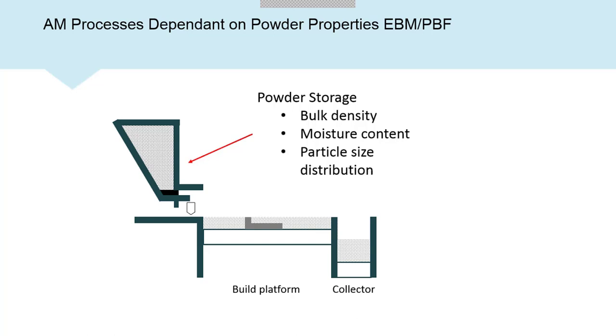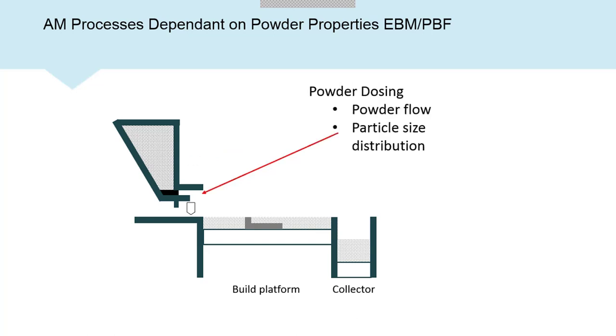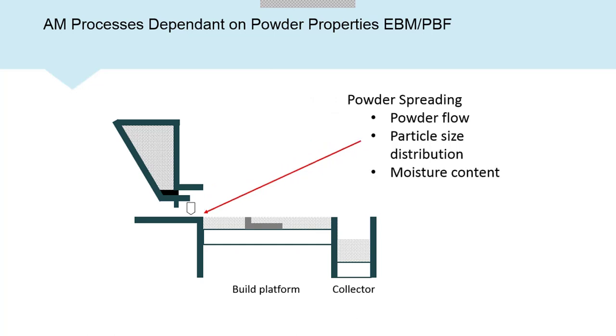In this scenario, bulk density becomes important, because obviously the lower the bulk density, the less material you can store, or the bigger container you're going to need to store the powder in. Moisture content, because that could cause bridging in the hopper. And then particle size distribution, so ideally you'd want no segregation, so you've got the same distribution from top to bottom. At some stage you need to dose your powder from that hopper into a dosing unit. So then I'm interested in powder flow. Will my material reliably flow from my storage hopper in front of my spreader? Will I get the same amount every time? Again, particle size distribution, will I be seeing any kind of segregation, which could give me varying part properties from bottom to top?